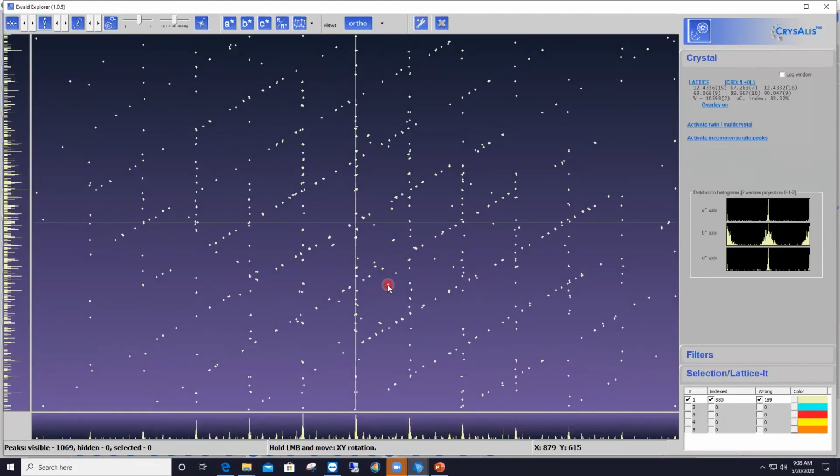The oblique rows of reflections are even better aligned. This is what I meant when I said I was looking for an orientation that would show me intertwined rows of reflections. So you have clearly two diffraction patterns here. Those rows of reflections crossing each other can never happen if you have a proper single crystal.